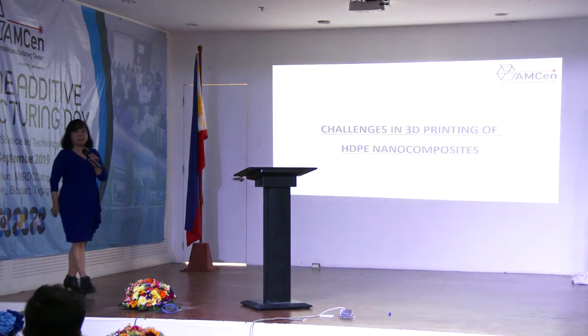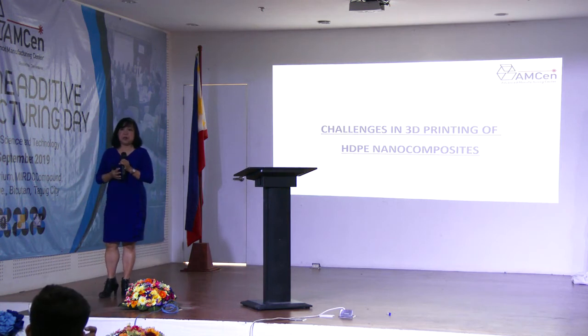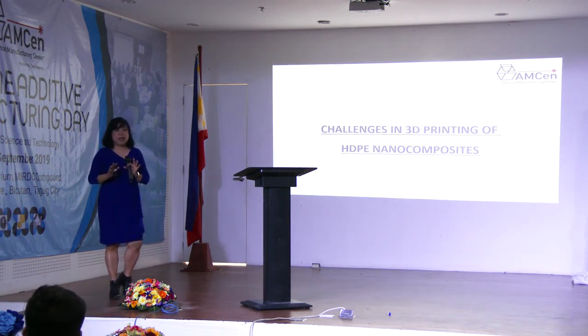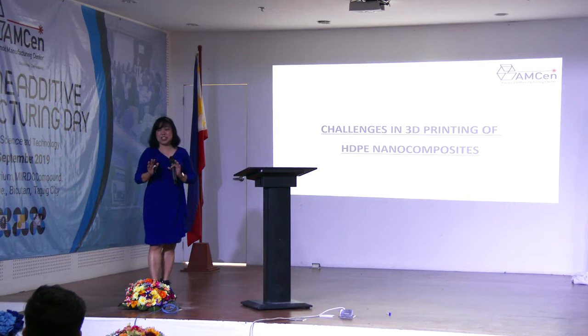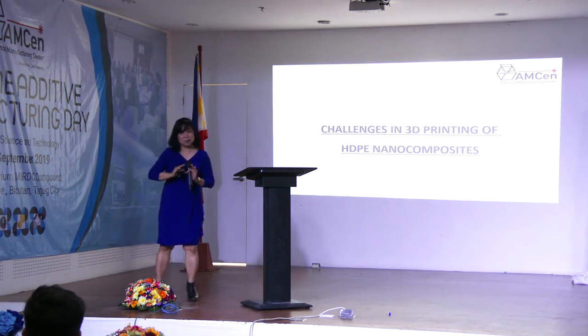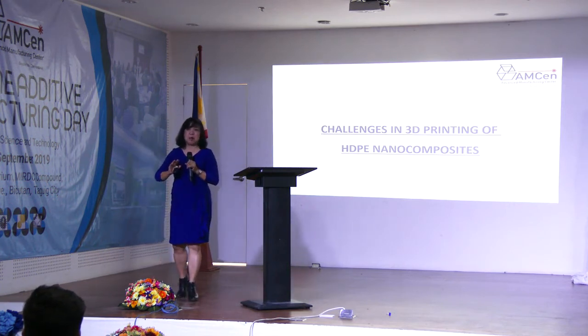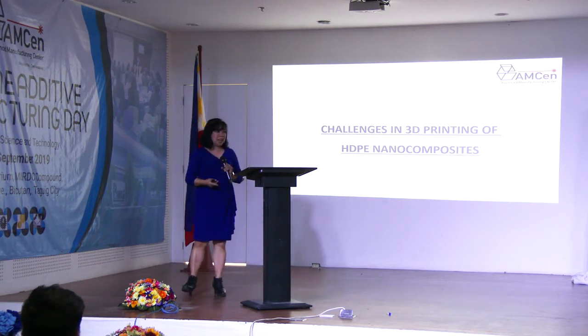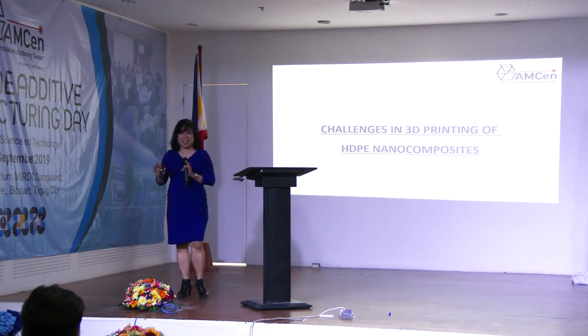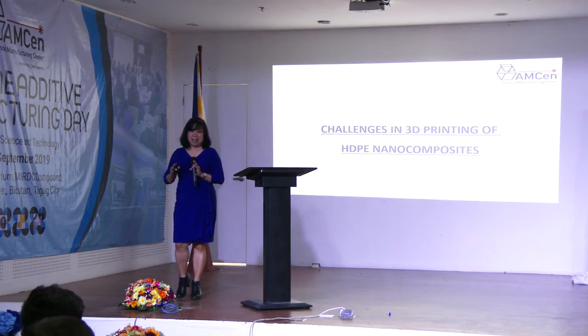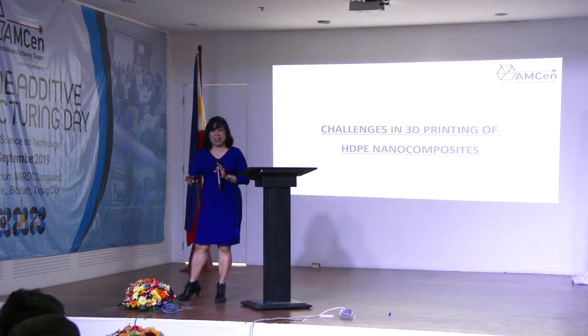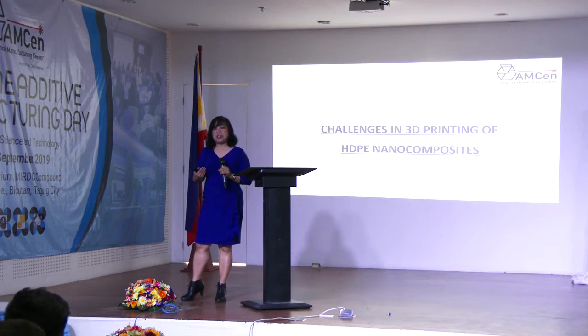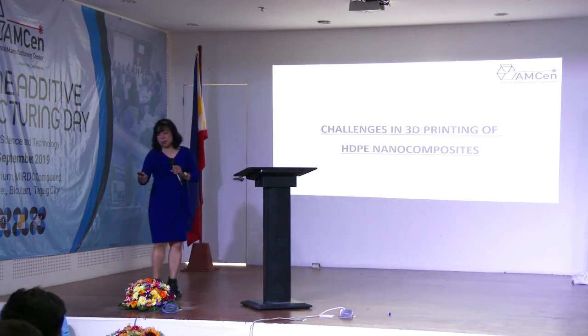But there are challenges in 3D printing. As you know, earlier it was discussed that 3D printing is easier when you use PLA, polylactic acid, which is mostly used in 3D printing, or ABS, acrylonitrile butadiene styrene, right? Because they easily stick on the build plate. In our case, it's the first time that we use HDPE, high-density polyethylene, as the matrix for 3D printing. And we encountered this problem.